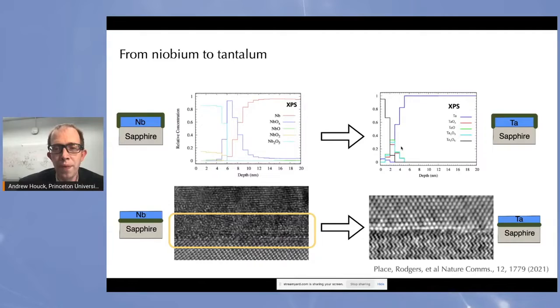And this sort of amorphous peak that goes between the oxide and the metal is nearly gone in these tantalum films. Moreover, if you look at the interface between the metal and the sapphire, things look absolutely ordered. And you can see this beautiful crystalline structure both in the metal and going directly down to the surface of the substrate. So we found a material system that allows us to address the kinds of interface and surface challenges that plague the field and lead to short coherence times that had been stagnated for so long at 100 microseconds.